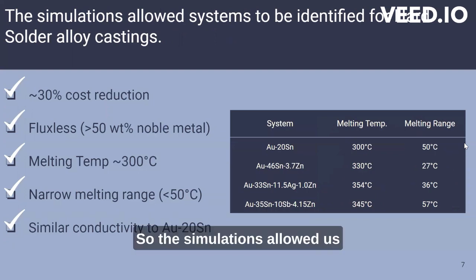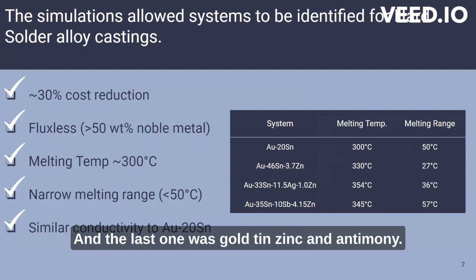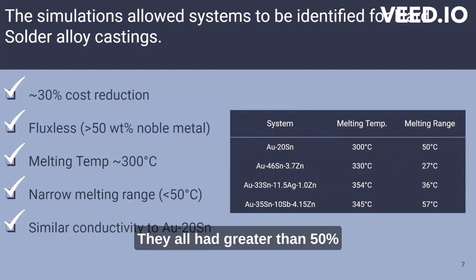So the simulations allowed us to identify three systems. One was gold, tin, zinc. Another was gold, tin, zinc, and silver. And the last one was gold, tin, zinc, and antimony. And these systems all had a 30% cost reduction. They all had greater than 50% gold.